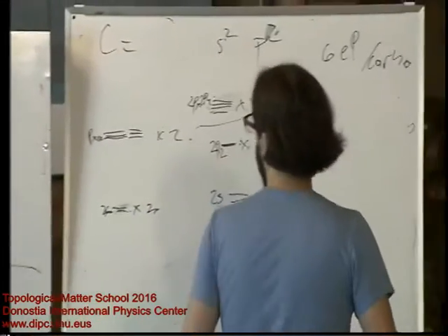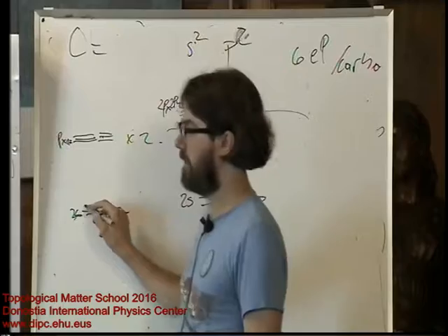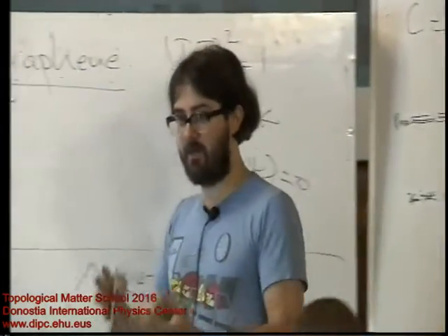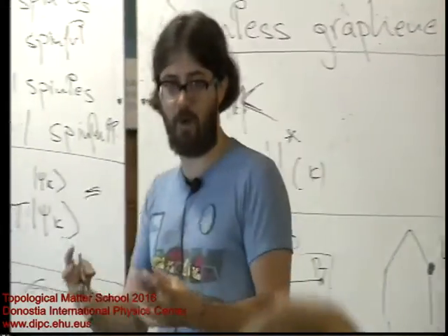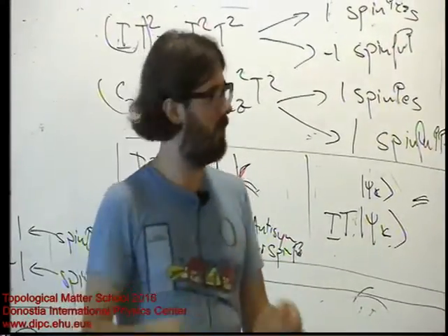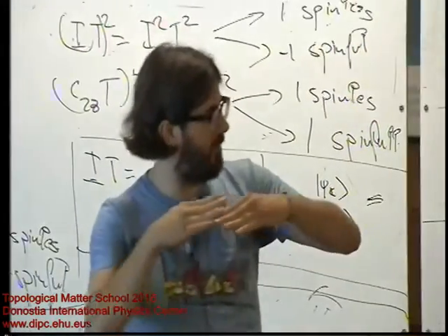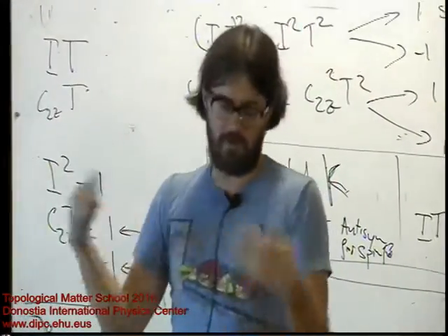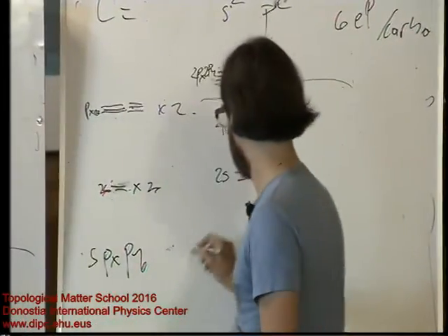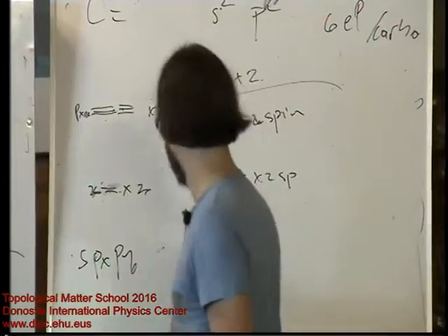Where I'm wrong is that the s and p orbitals, px and py, hybridize. They have hoppings. And in graphene, unlike in bismuth, or bismuthene, or other things, they're so close together, the bonds are so strong, that they form a new set of orbitals, sp2. So the s, px, and py orbitals form sp2 orbitals in graphene.